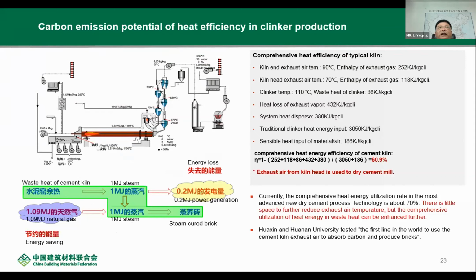Let's look at the aspect of improving clinker heat efficiency. As we introduced previously, the heat consumption of a typical modern NSP is about 740 kilocalories, and carbon emissions can be reduced if we simply use the system. However, we can see more from the full system, including the steam generated from the clean exhaust gas. We use this steam to generate power, which can bring some heat efficiency. If we can use this steam to manufacture some building material products, the heat efficiency can be improved to a much greater extent. Heat efficiency improvement means a reduction of system carbon emissions.